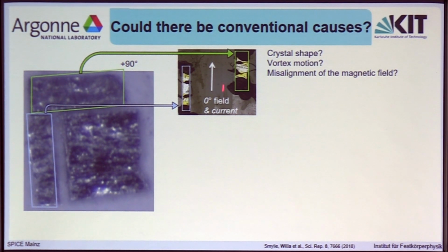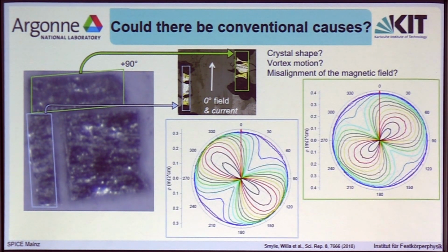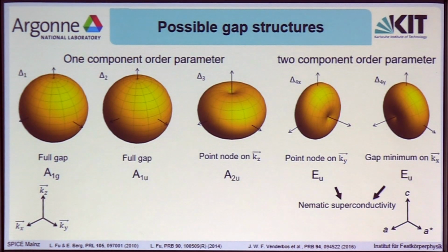And we've done transport measurements, so we could monitor these shapes here for constant temperature field sweeps in the plane. And also you can directly see that those are not pointing in the same direction, and we thus exclude those things here being responsible for this anisotropy. So, if there are no conventional sources, let's consider the theory options of the superconducting gap structure.